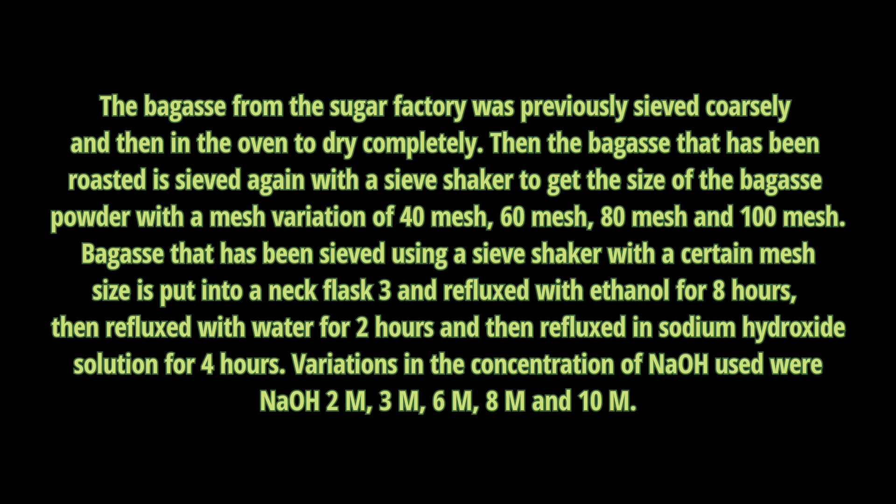The bagasse is refluxed with ethanol for 8 hours, then refluxed with water for 2 hours, and then refluxed in sodium hydroxide solution for 4 hours. Variations in the concentration of sodium hydroxide used were 2M, 3M, 6M, 8M, and 10M.